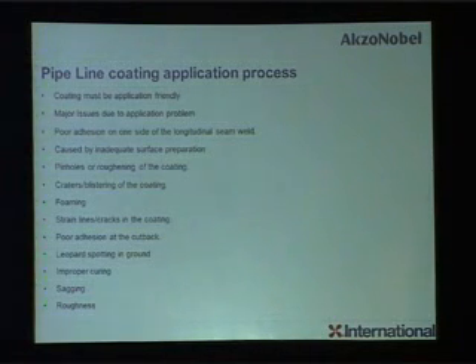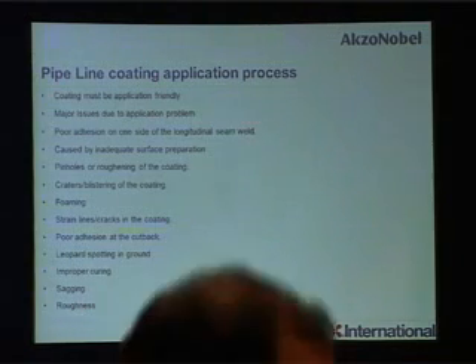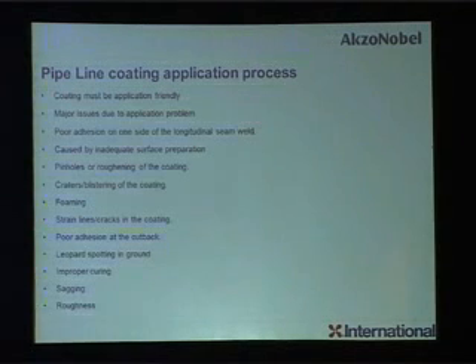Poor adhesion on one side of the longitudinal seam weld. This is another major problem we have seen during our visits, our witness at site. Caused by inadequate surface preparation, definitely that, sir, you have already highlighted. Pinholes or roughness of the coating, blisters, foaming, stain lines, poor adhesion at the cutback, and sagging, roughness, and all those things. So these are the things during the application, even if your coating is very nice, you may encounter all these types of problems. So all these problems, we need to ensure a proper standard application procedure to avoid all those things.